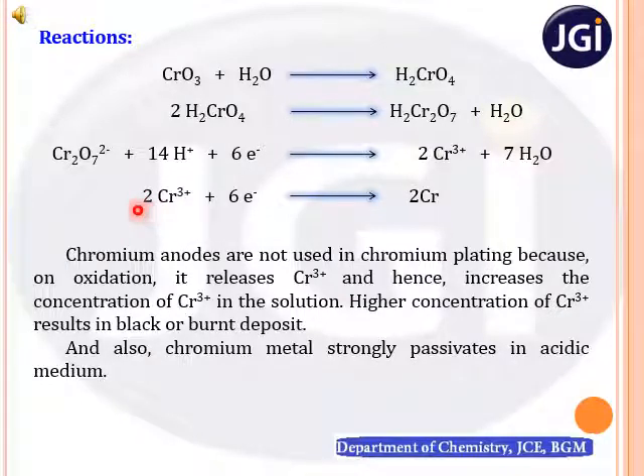The concentration of this trivalent chromium ion plays an important role in the electroplating. If you have a higher concentration of Cr3+, we will not get uniform deposition. Now this Cr3+ further undergoes reduction by accepting electrons from the external source and gets reduced to chromium metal, that is 0 oxidation state, which gets deposited on the cathode surface. It means the chromium in the electrolytic bath is reduced from +6 oxidation state to 0 oxidation state in 2 steps, and finally gets deposited onto the cathode surface. I hope this is clear.